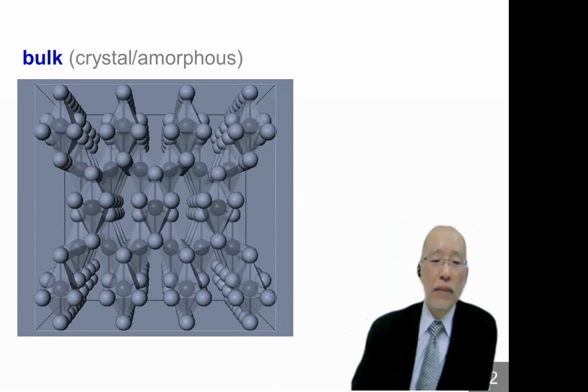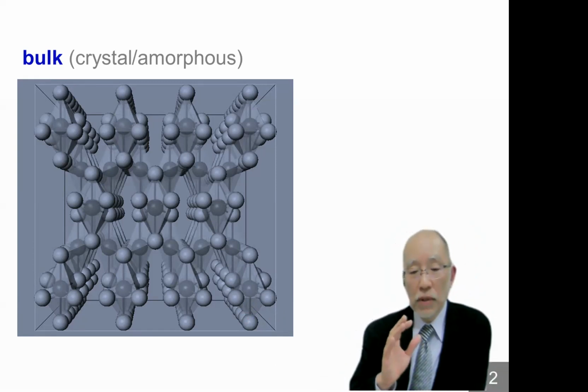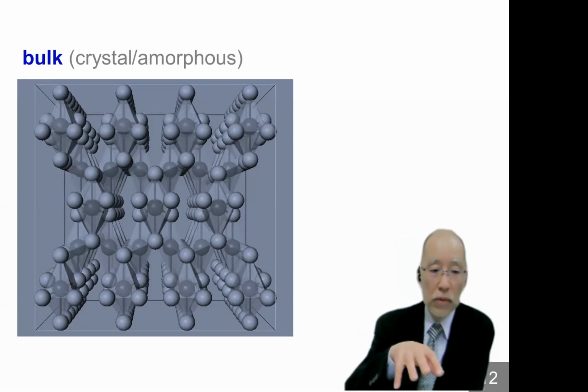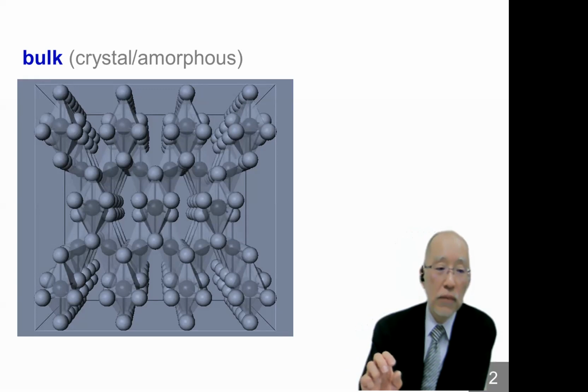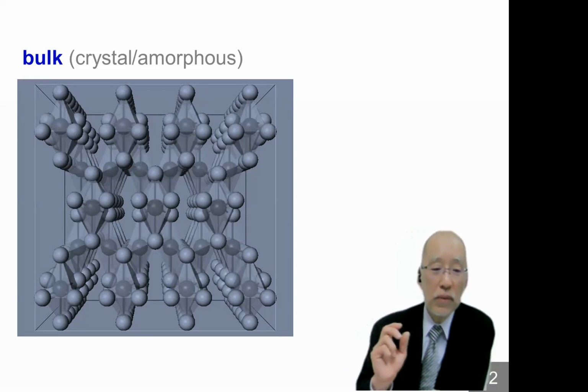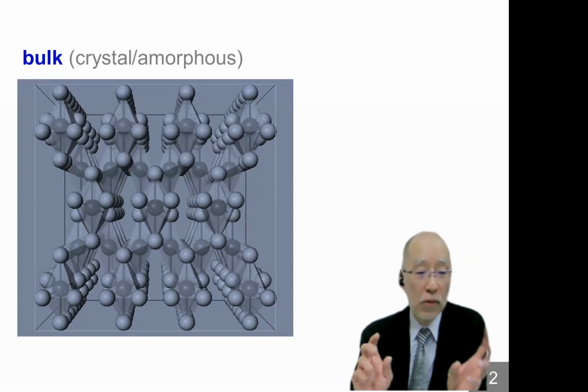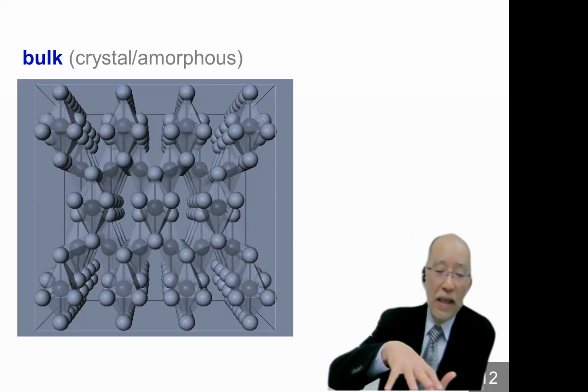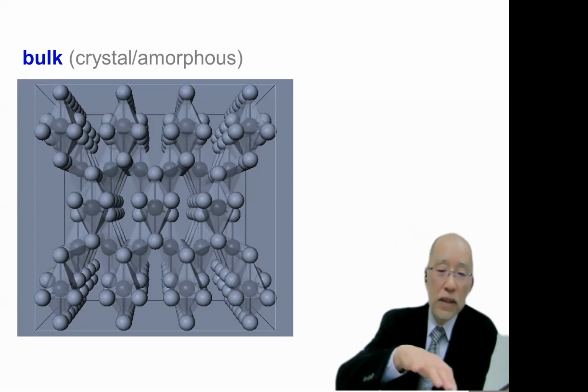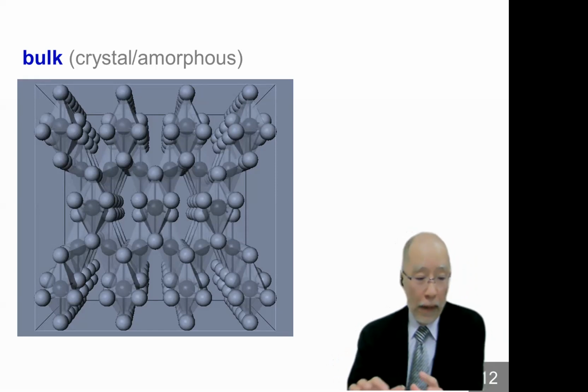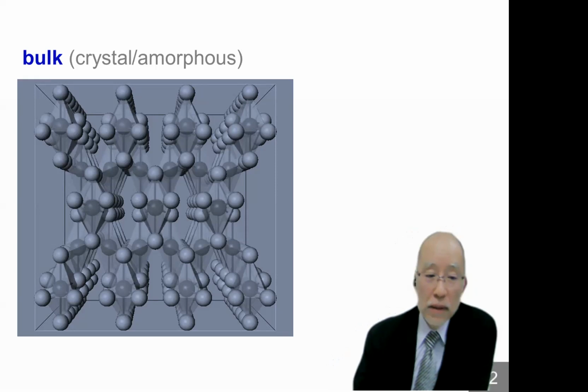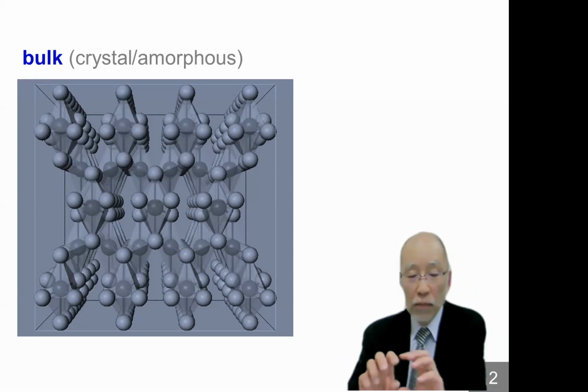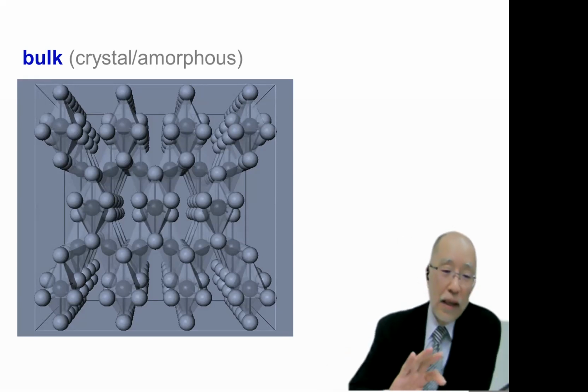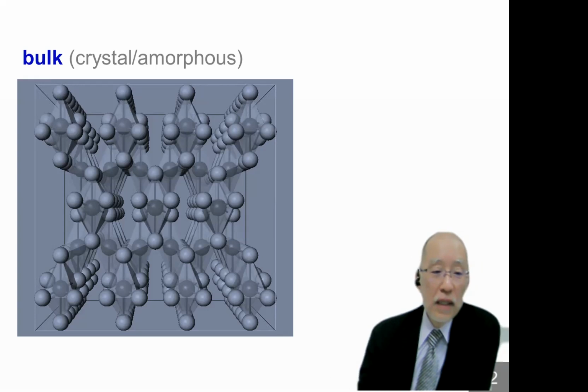And for crystalline material, it is possible to determine the contents, how much amount is included, and the rest must be non-crystalline phase. But for those non-crystalline parts, it is impossible to determine what kind of compounds. Even if the titanium oxide crystal are surrounded by the amorphous non-crystalline material, there is no guarantee that those parts is the same composition as TiO2. Another composition can be. So therefore, even for bulk structure, it is not so easy to determine correctly.